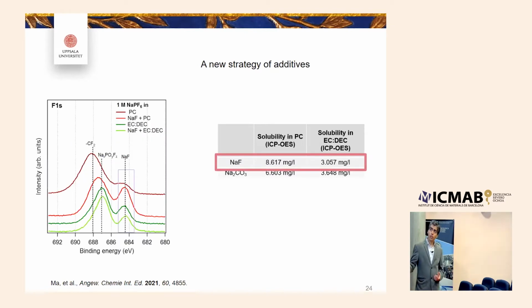So we saturated the electrolyte and did XPS on the negative electrode. What we could see is that the red ones are PC electrolytes, unsaturated and saturated with sodium fluoride. And when I say saturated, I'm talking about ppm level. So what we did was use this amount to saturate the electrolyte, then filtered the extra remaining amount. We can see there's a clear difference in the PC electrolyte.